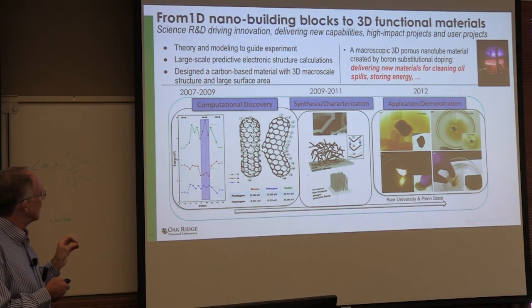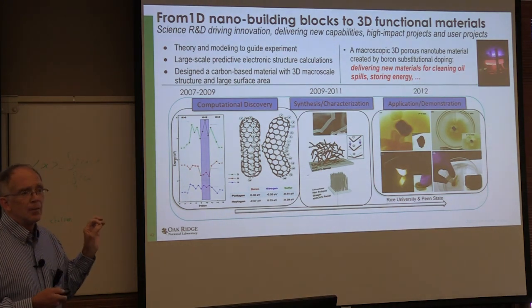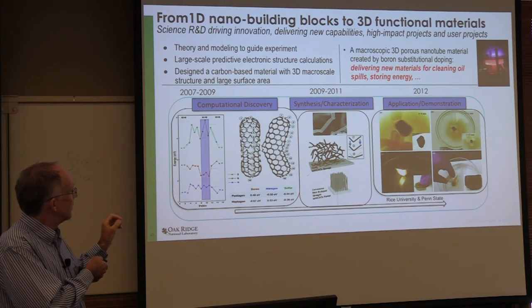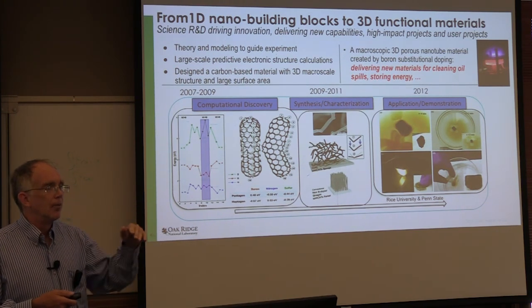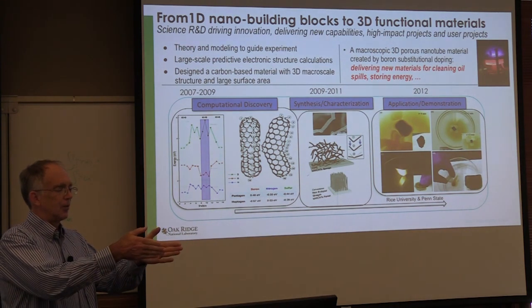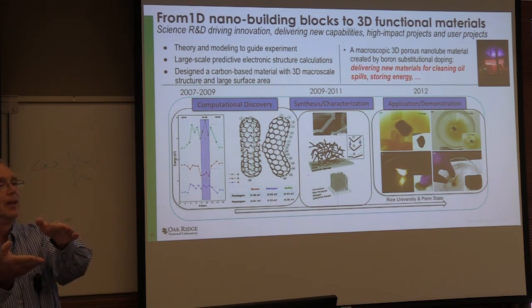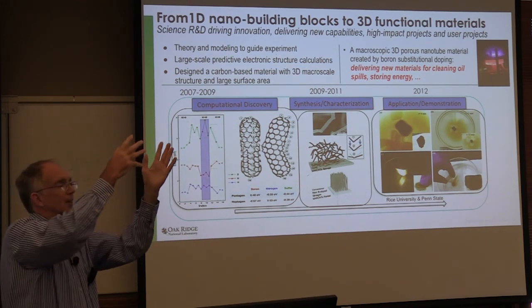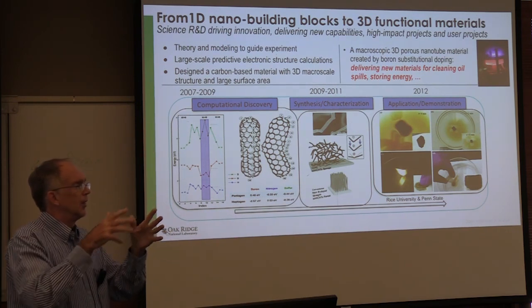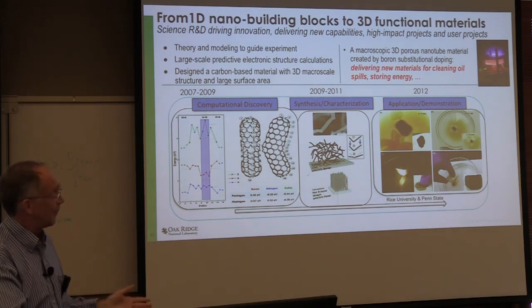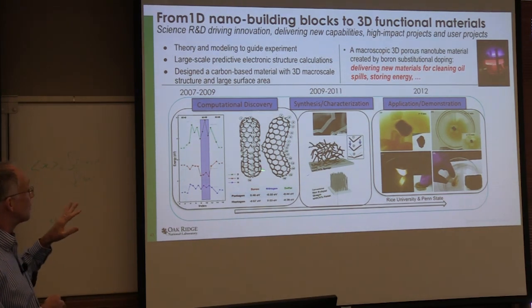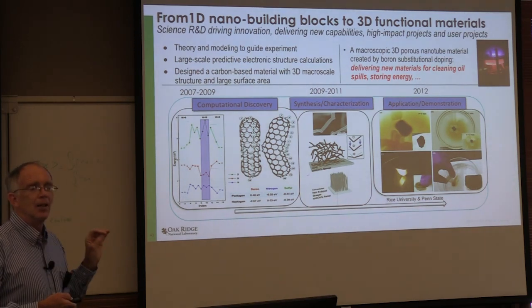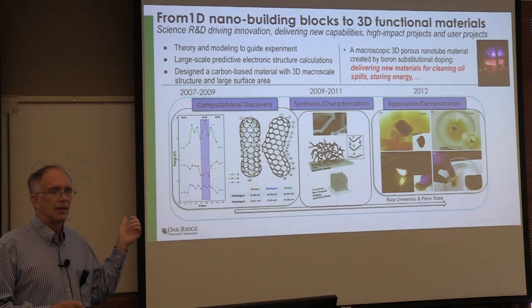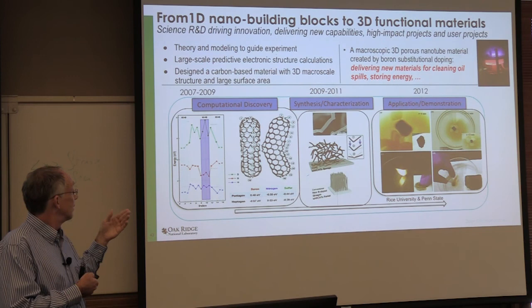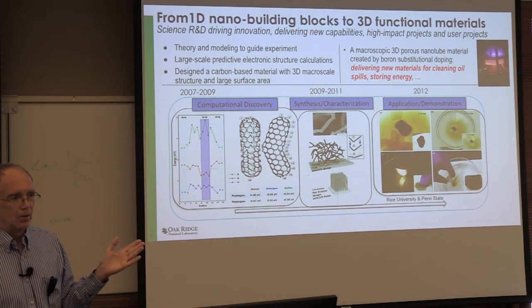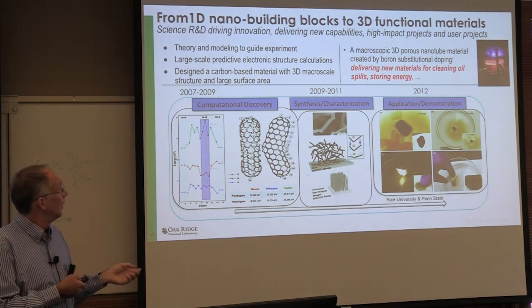Our discovery was that if you put boron in here, it'll mostly want to be inserted into the lattice at a turn. So instead of having a straight tube, you have a tube that grows to a certain point, boron gets inserted, and it changes its direction and keeps growing, changes its direction, keeps growing. In principle, you would get this highly curved carbon nanotube structure that goes on for very long length scales. Nice idea, right? All we've done is ask what the energetics of putting those atoms in are. We calculated that using the electronic structure calculation, solving that stationary Schrodinger equation, got these energetics, and found that, yeah, why don't you use boron? So you can use boron as one of the precursors in this chamber with carbon and grow your carbon nanotubes.